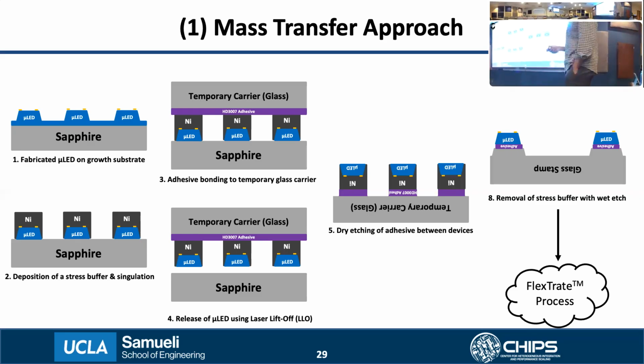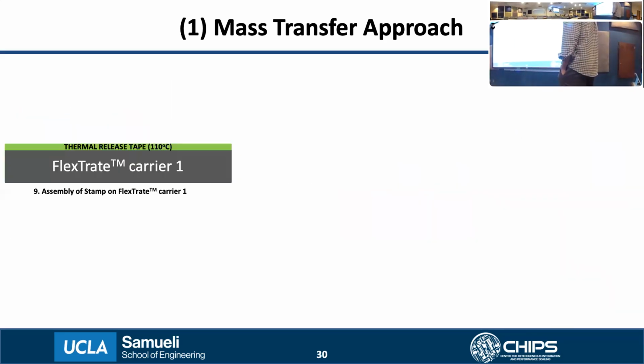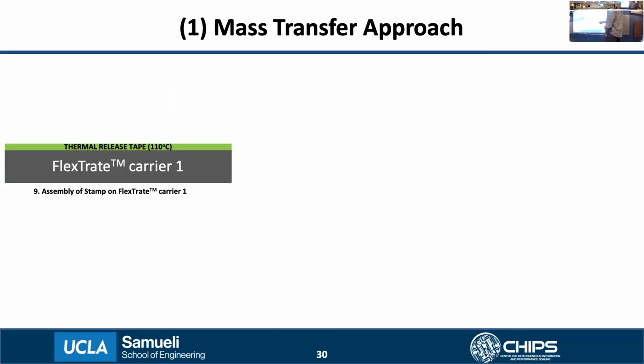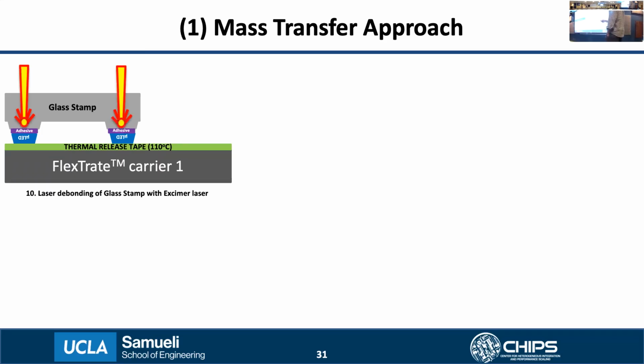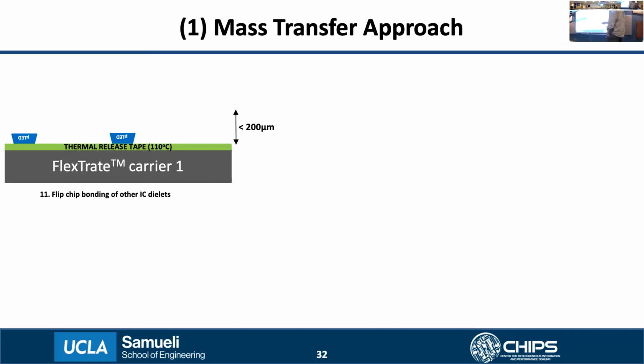So next we move on to the FlexTrate process. In the FlexTrate process, as shown in step 9, we have a FlexTrate carrier, which could be a silicon or a glass wafer, on top of which we laminate a thermally releasable adhesive tape, which has a release temperature of around 110 C. We then flip chip place the LEDs on the stamp onto this, and then we do a final laser debond step with an excimer laser to transfer the devices completely onto this thermal tape.